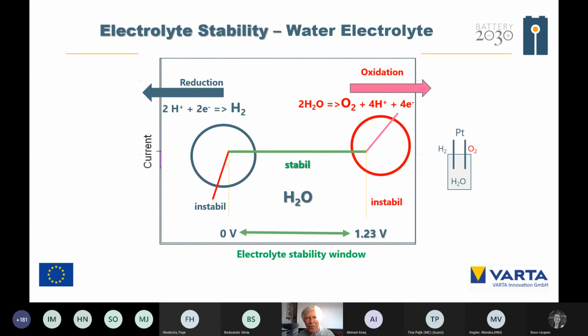To understand what is going on with the electrolyte stability, take the well-known example of water. You have two platinum electrodes, and if you go to the lower potential at about 0 volt, hydrogen is generated. So in that region the water is unstable, and going in the positive direction at about 1.23 volts, the water is oxidized to oxygen. So only in between do we have the electrolyte stability window.